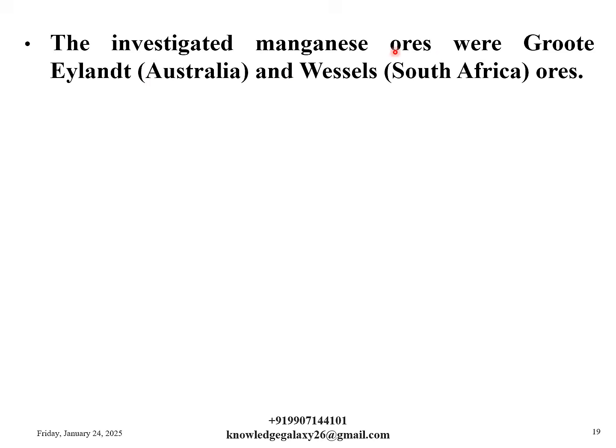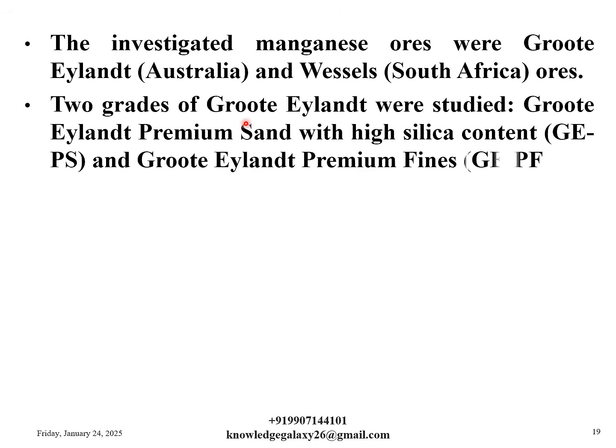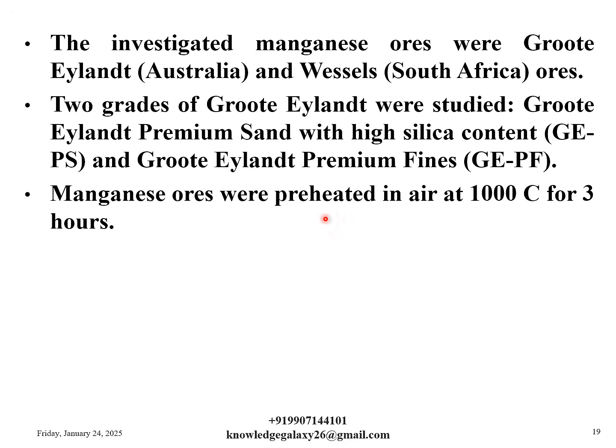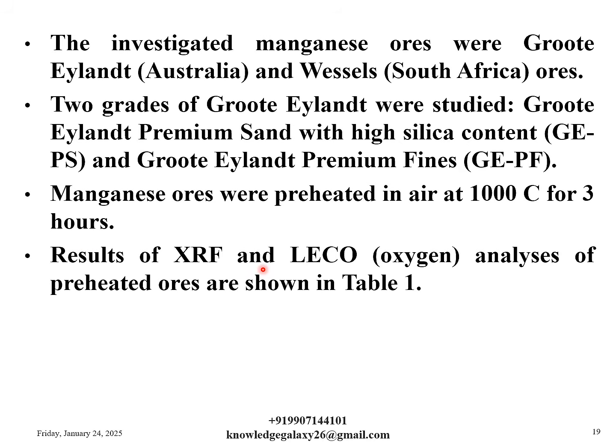The investigated manganese ores were Groote Eylandt, Australia and Wessels, South Africa ores. 2 grades of Groote Eylandt were studied. First one is Groote Eylandt Premium Sands with high silica content, GEPS, and Groote Eylandt Premium Fines, GEPF. Manganese ores were preheated in air at 1000 degrees Celsius for 3 hours. Results of XRF and LECO, that is oxygen analysis of preheated ores, are shown in the table in the next slide.